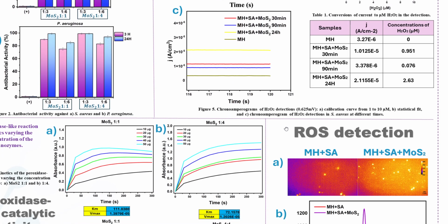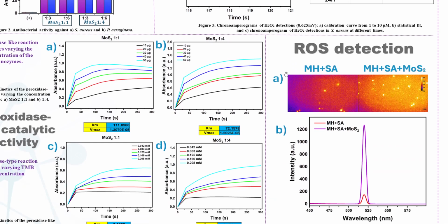To further investigate the mechanisms, we performed fluorescence-based ROS assays. Here we can compare Staphylococcus with the molybdenum disulfide, and a clear increase in the fluorescence intensity is observed in the presence of molybdenum disulfide. The fluorescence spectrum also simultaneously increased around 529 nanometers, linking peroxidase activity to antibacterial activity.